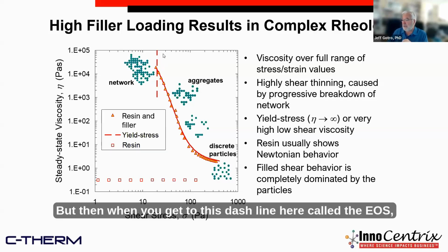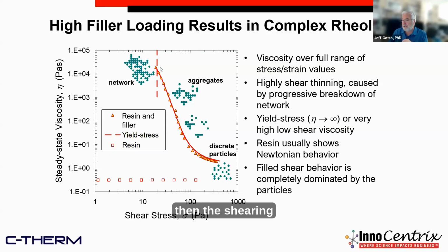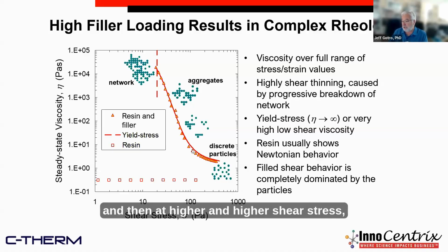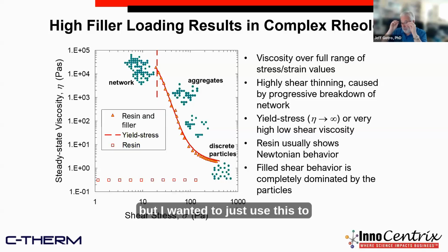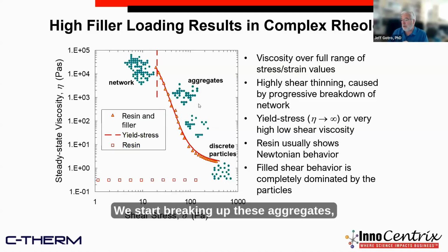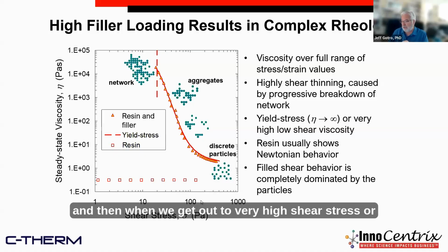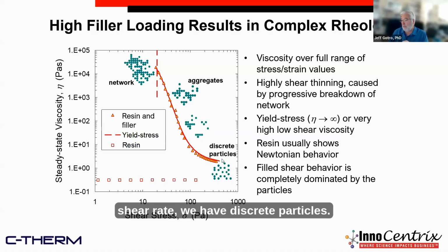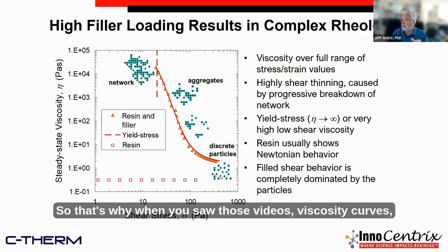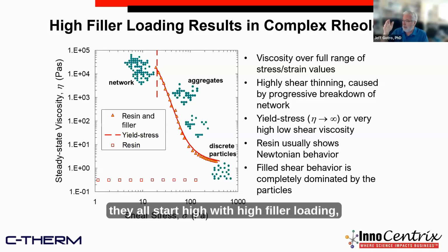But then when you get to this dashed line called the yield point, the shearing forces start to break up the network and form aggregates. And then at higher and higher shear stress, this is stress now, we do a little bit different experiment, but I want to use this to illustrate the point. We start breaking up these aggregates, and when we get out to very high shear stress or shear rate, we have discrete particles. So that's why when you saw those viscosity curves, they all start high with high filler loading, and they come down and sort of level out.